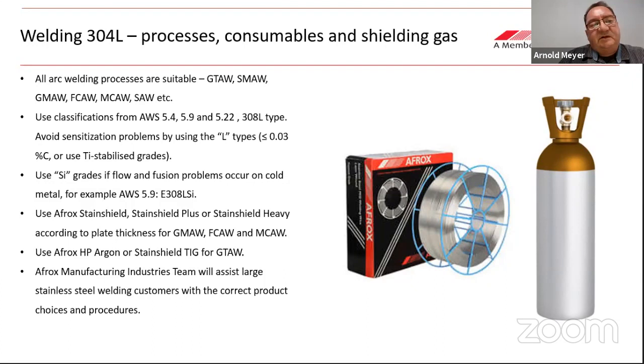You must avoid sensitization problems by using the L types. In other words, in the welding rod, it will be less than 0.03% carbon. You also get titanium stabilized grades, where the carbon will rather react with the titanium than with the chromium. If you have flow problems, a little bit of silicon will solve that problem, especially when you do MIG welding. It's useful to go to a 308 LSI.